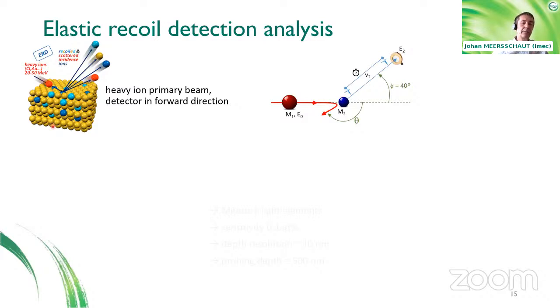The amount of scatterings or recoils is so low that during the experiment, you can still consider that the sample is being unchanged. One difficulty that you could recognize is that when you have different types of ions being emitted from the sample, and they have also different energies because they emerge from different depths, that you don't know which ion species is coming from which depth.